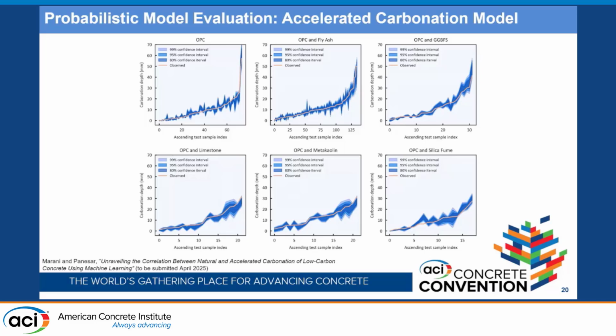But what I'm trying to show here is that the model is able to find the uncertainty in the predictions. Here we have 80% confidence interval, 95% and 99% confidence intervals. And we can see, depending on the type of SCM that we have, we could have different uncertainty in the predictions, which could be related to the source of the data or to the number of data points that we had. As you can see, for some cases like silica fume or limestone, we didn't have that much testing data. But for example, for slag and fly ash, we had more data points, which could increase the certainty or reduce the uncertainty in the predictions.